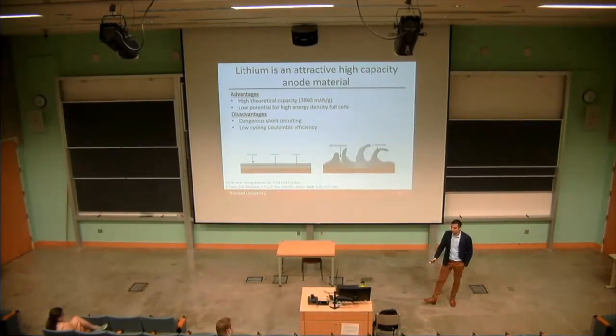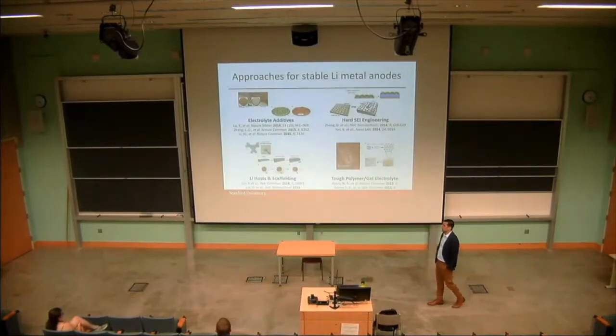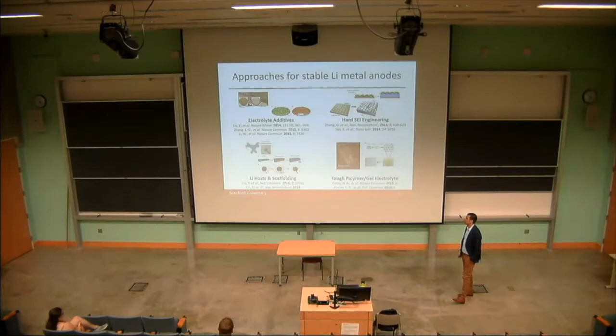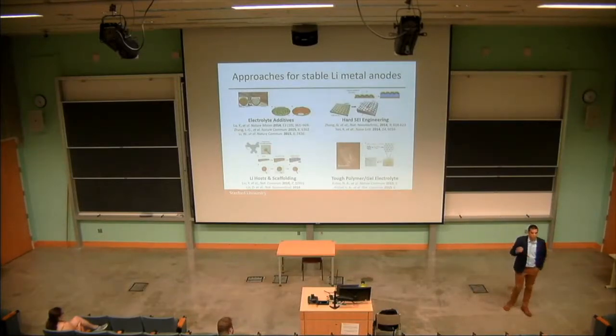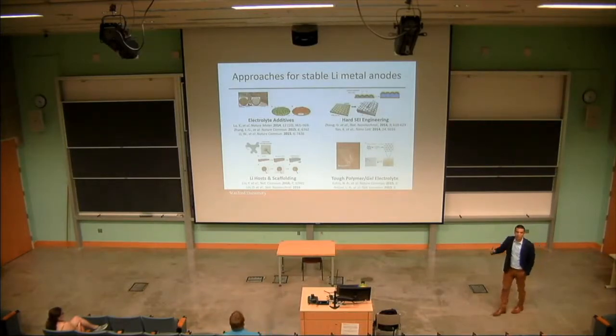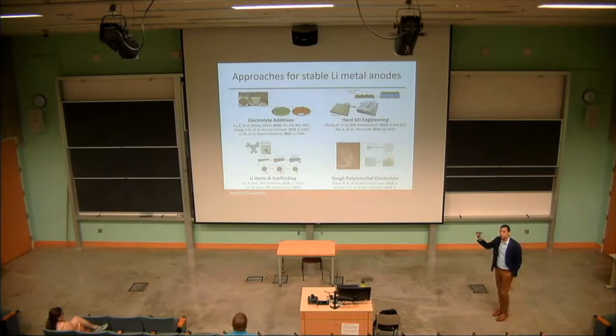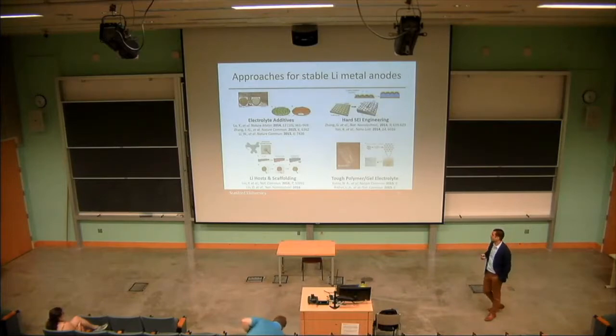can achieve. To do this, there's been really a wide variety and a lot of activity in recent years of research in this area. One of the most popular, because it's so simple and straightforward, is using additives in your electrolyte. So you can take a standard liquid electrolyte, carbonate or ether-based, typically with your lithium salt, and you can add in some other molecule that will then preferentially decompose on your lithium or perform some other function to change how your lithium is growing on the surface.